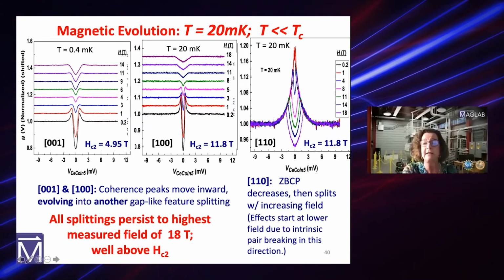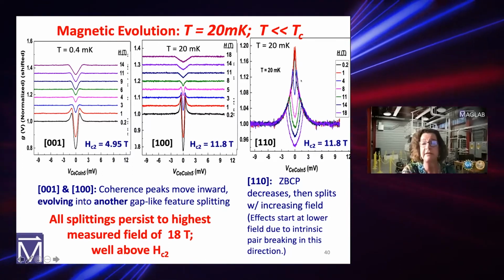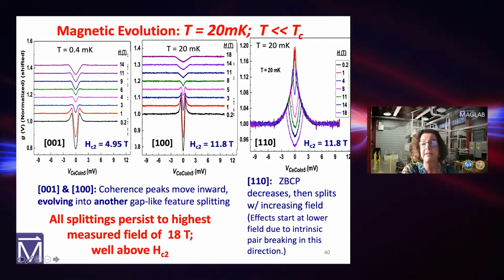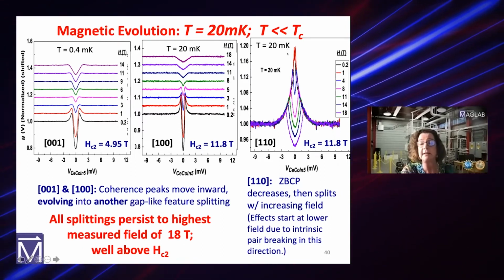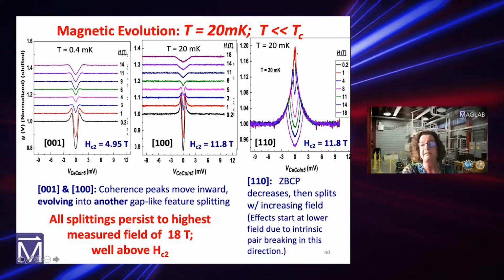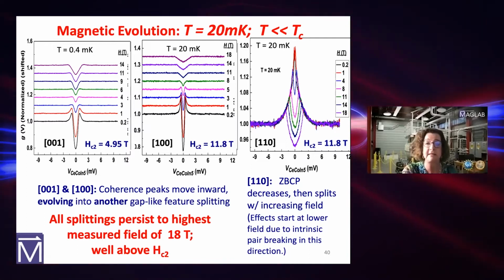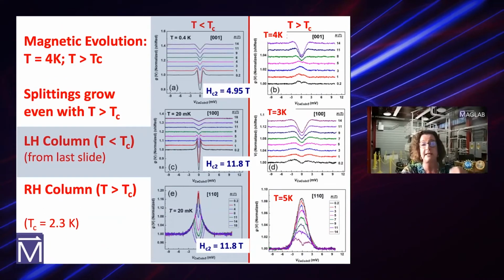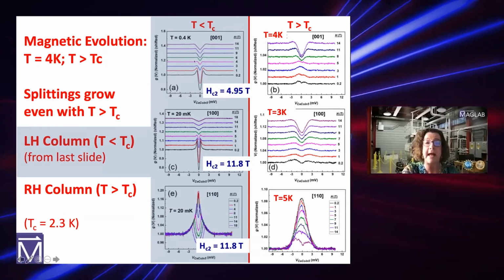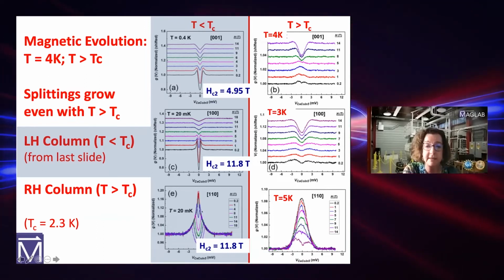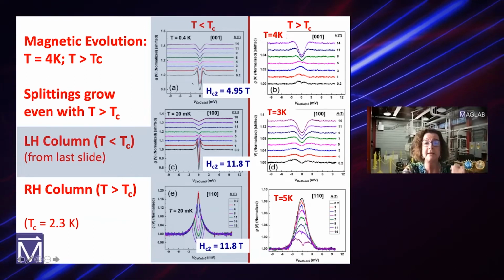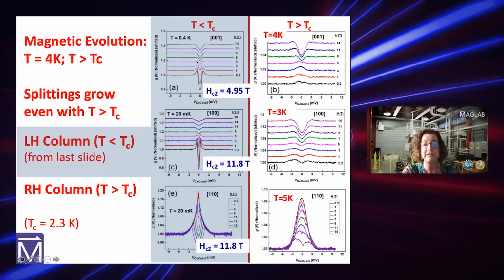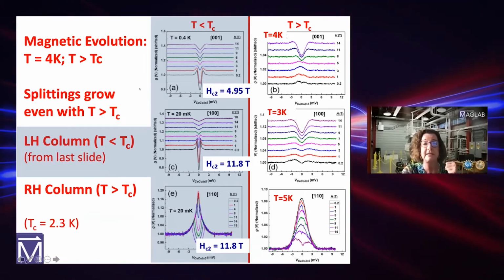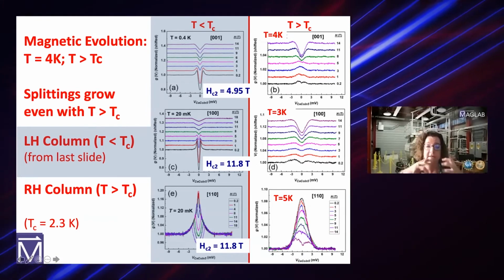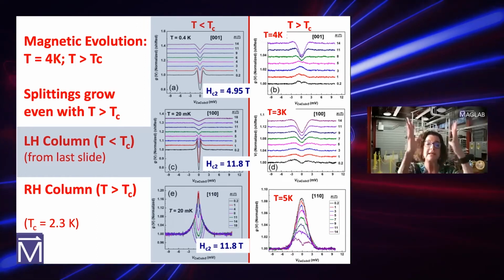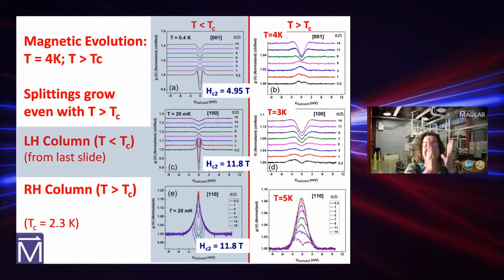This is more complicated to understand in the nodal direction. All we can tell you is that we have an understanding, I won't have time to explain it here, that we do see this splitting more quickly with applied field. And that's probably because there's very few Cooper pairs in that direction anyhow, because that's the nodal direction. Now, I want to point out something in this magnetic evolution. We showed increased gap formation when you go above. So right now, everything in gray is what I just showed you. These data were all taken at low temperature, and this is the correct temperature listed here, and as you raise the field, we see the superconducting gap go away, and smoothly another gap, we call it a FIG, a field-induced gap, starts coming in.